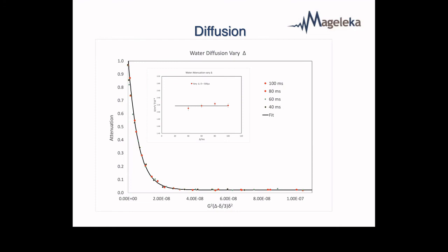Now think about water inside a pore. Water inside a pore can only traverse the diameter of the pore. So again, from the diffusion coefficient, we can measure the internal diameter of the pore. And that also gives us a handle on calculating this Ka parameter I mentioned before. So combining the diffusion experiment and the relaxation experiment, we have an absolute method for measuring surface area.